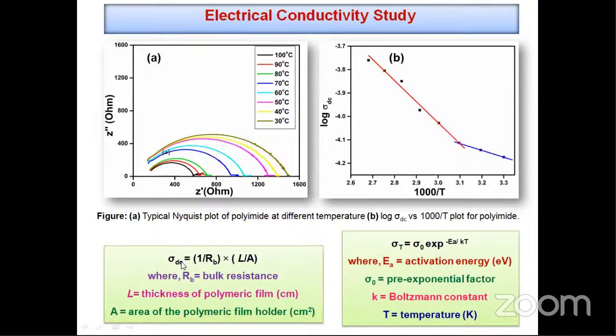The dc conductivity of the polyimide is calculated as 10 to the power minus 5 Siemens per centimeter at room temperature, which increased up to 10 to the power minus 4 Siemens per centimeter at higher temperature due to increase in chain flexibility at higher temperature. Figure B represents the temperature dependent dc conductivity. The temperature dependent dc conductivity shows Arrhenius type behavior, and here the conductivity increases with increasing temperature and follows Arrhenius like behavior with a thermally activated process.